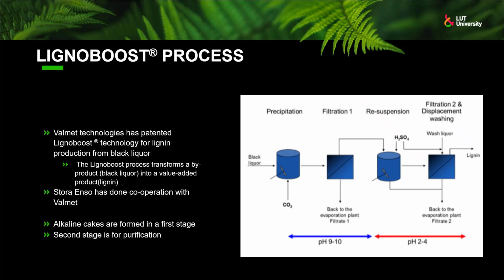LignoBoost process. Valmet has patented LignoBoost technology for lignin production from black liquor. The LignoBoost process transforms a byproduct into a value-added product. This LignoBoost process consists of 2 filtration lines. The first filtration stage produces alkaline cakes at a pH of 9 to 10, and the second stage produces purified cakes at a pH of 2 to 4.